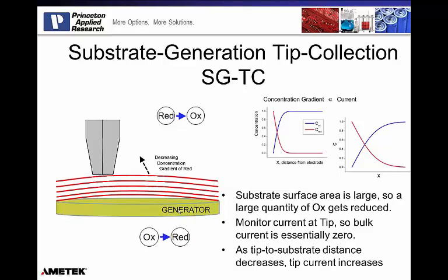And so if I take a generator sample, again, I'm going to use this whole disk. I've made my solution to be solely 3+ iron in the beginning, so ferricyanide. Now I've applied a reducing potential to that gold sample surface. And so what that does then is it causes iron 3+ to go to iron 2+, all on the sample surface. Since iron 2+ does not exist in the bulk state of the solution, diffusion is going to take control, and that iron 2+ then is going to diffuse away from the sample surface.